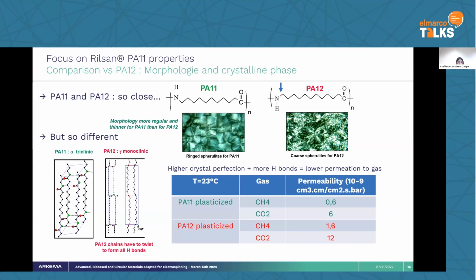But also here, I thought that maybe it could be interesting for some of your applications. Due to this more regular and thinner morphology, when you look at gas selectivity and permeability, and you compare PA11 and PA12 with similar molecular weight, you see that with polyamide 11, we can have a better selectivity and lower permeation compared to polyamide 12.